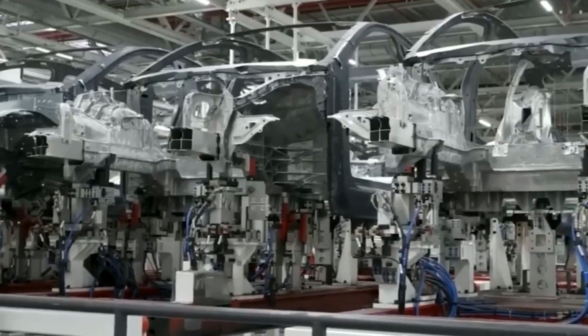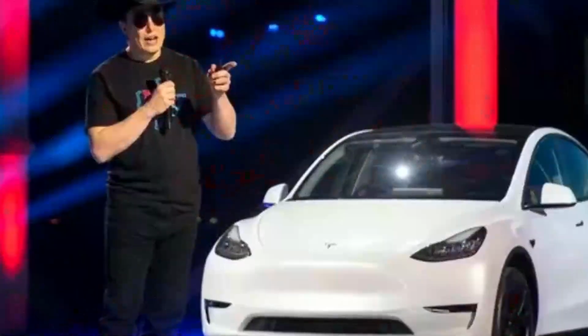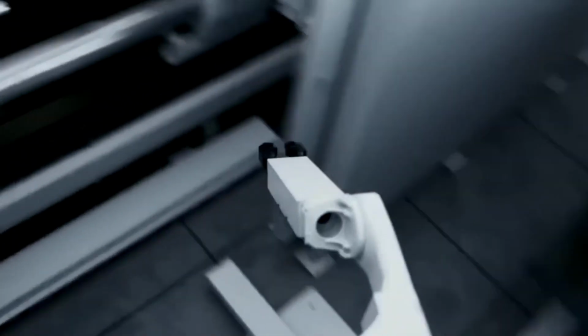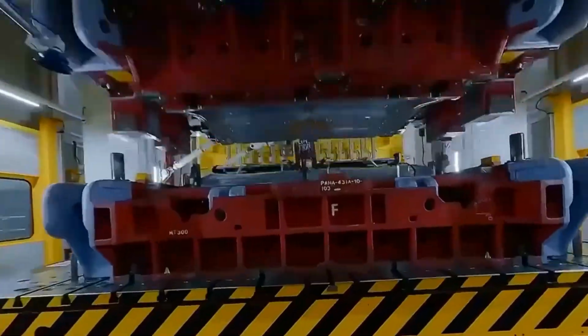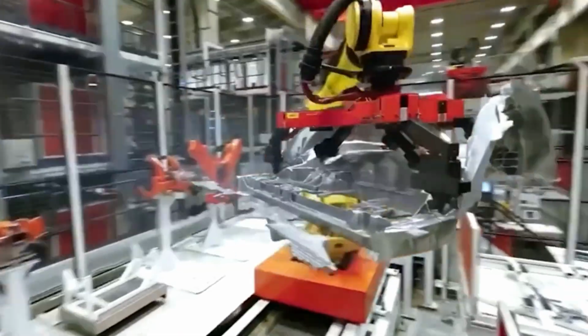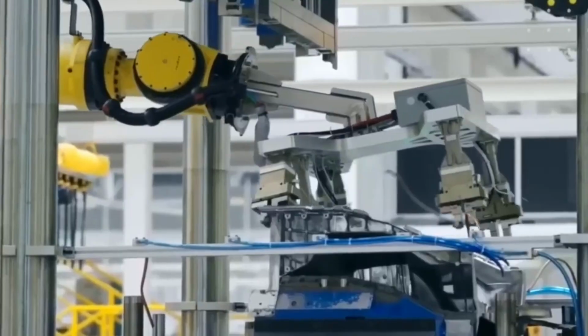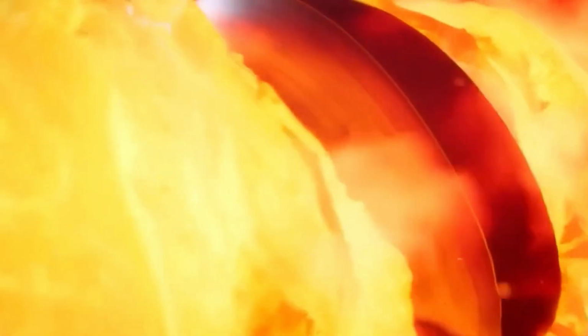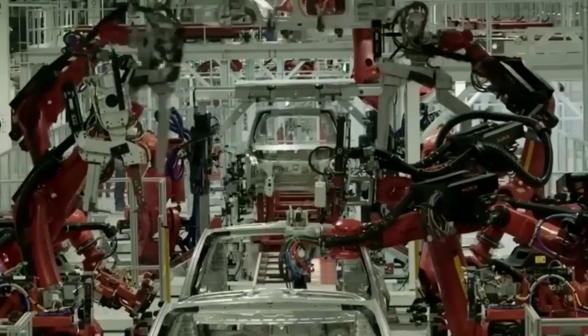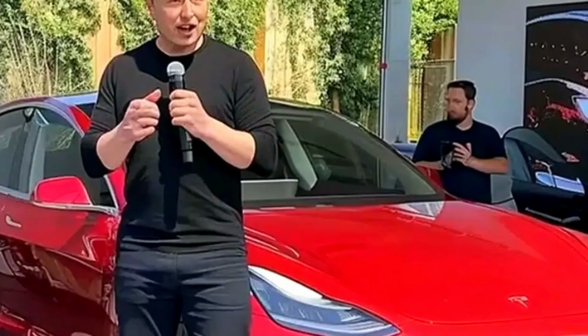But molten aluminum isn't passive. It reacts with its environment and can trap gases or pick up unwanted particles during the process. To address this, the system uses a controlled gas environment, argon degassing, and silicon carbide filters to bring the metal to the required purity level before it ever touches the mold. Once the metal is ready, the mold itself is prepared. A thin layer of lubricant is applied to every surface to ensure clean part removal. Then a vacuum is drawn inside the mold cavity to eliminate trapped air. Because at this scale and speed, even a small pocket of gas inside the casting can compromise the structural integrity of the finished part. Then the piston fires.